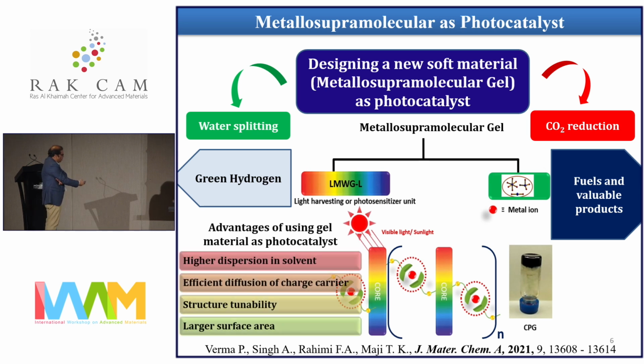When you put such kind of soft material in the solvent, it will give higher order dispersions, efficient diffusion of the charge carrier, structural tunability, and a large surface area. As I told you, you have the core, which is the pi-chromophoric linker, that can act as the light harvesting moiety to the metal ion. But in reverse electron transfer, sometimes the metal complex can also act as the light harvesting moiety, and your core can act as the catalytic site.